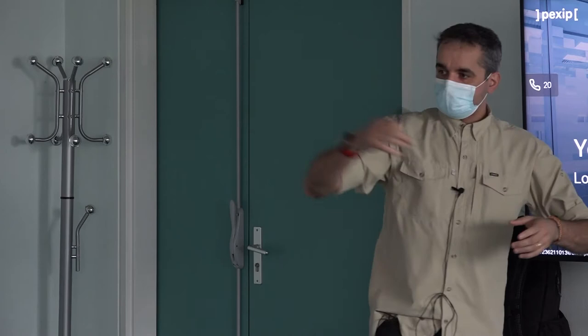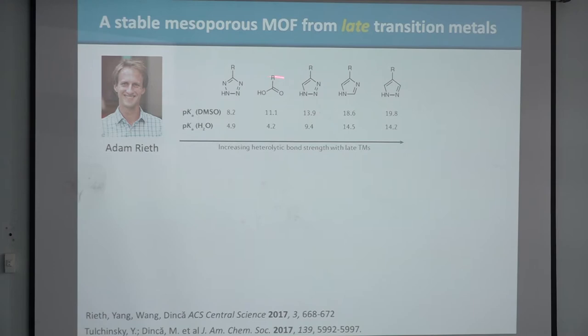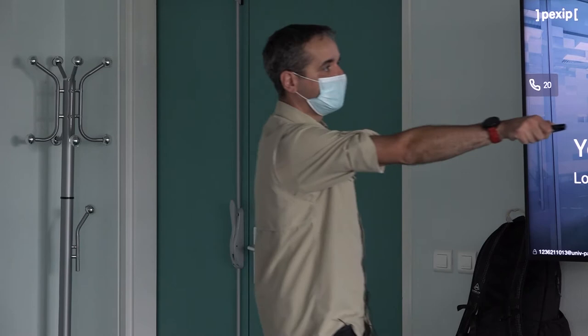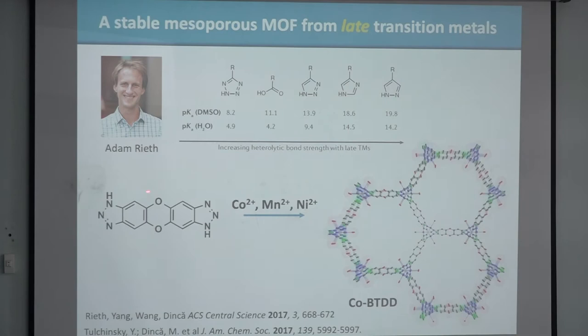We didn't want to work with zirconium because it's not a very interesting metal for catalysis. We want to work with late transition metals, but unfortunately those tend to be labile, so you need to use both thermodynamics and kinetics. Instead of carboxylates, we went to azoles — putting in nitrogens to get something like pyrazole or imidazole, which are very weak acids. That means the imidazolate or pyrazolate anions are very strong bases, so the metal-ligand bonds are stronger.